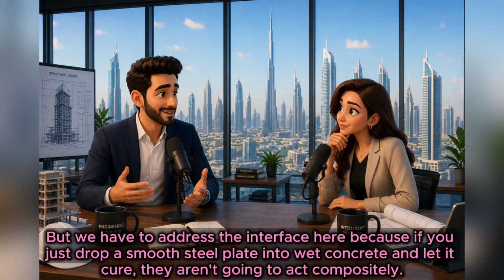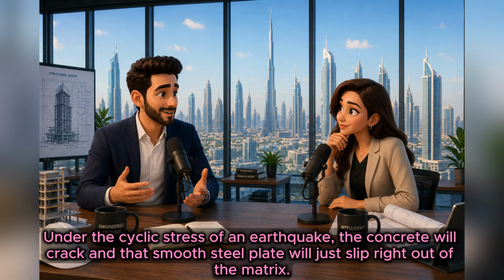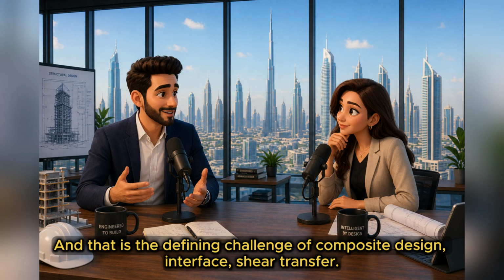But we have to address the interface here, because if you just drop a smooth steel plate into wet concrete and let it cure, they aren't going to act compositely. No, they wouldn't. Under the cyclic stress of an earthquake, the concrete will crack, and that smooth steel plate will just slip right out of the matrix. And that is the defining challenge of composite design: interface shear transfer.